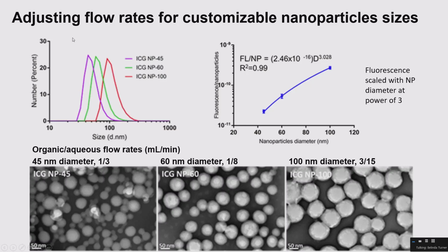So just quickly, not surprisingly, we figured out that by adjusting the flow rates, we could customise the size of these nanoparticles. And also we wanted to test whether the dye was actually being encapsulated versus being absorbed onto the surface of nanoparticles. So as the nanoparticle size increased, the fluorescence also scaled with the nanoparticle diameter at a power of 3, which indicated that it was being encapsulated rather than just being absorbed onto the surface, which would be scaling at a power of 2.